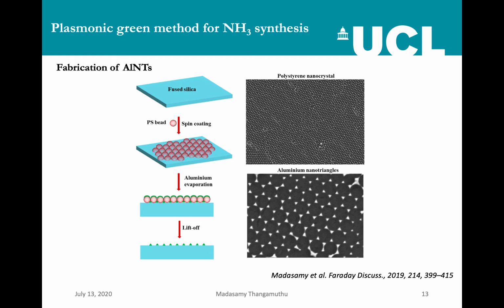So in my case, I decided to prepare aluminum nano triangles using the colloidal lithography method. So these are the steps involved in colloidal lithography. We have to take the fused silica substrate, and then we spin coat the polystyrene beads. Once the spin coating is done, or one can also do the same thing with the Langmuir-Blodgett technique, we get the polystyrene nanocrystal. On the right hand side is an image of the polystyrene nanocrystal. This is how it looks in the real case on the substrate. And then we deposit, let's say, 50 nanometers of aluminum on top of this template, and once we lift off the polystyrene beads, we will get this type of nano triangles that you can see in the SEM image shown here. So this is how I prepared it.